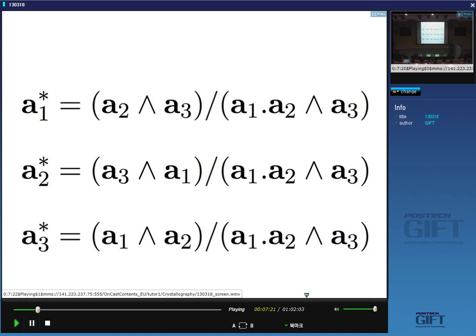Okay. Happy with that? Okay, so now you'll begin to understand why in Miller indices we take the intercept of a plane and then we take the reciprocal of those intercepts to define the Miller indices of a plane, because those are the components of a vector in reciprocal space. And the magnitude of that vector is 1 upon the spacing of the HKL planes, and it points at 90 degrees to those planes.